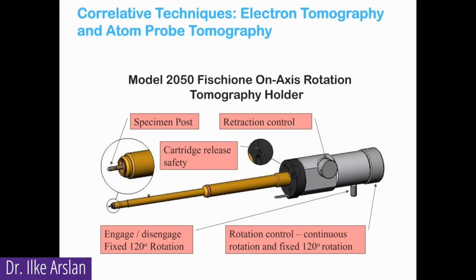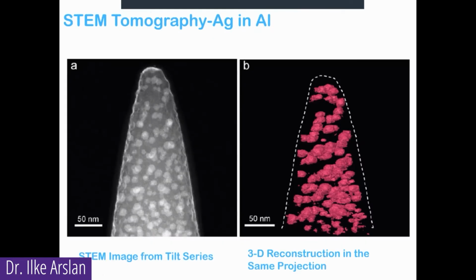And we used this holder that has this removable tip that can fit into a FIB so that you can make your sample and put it on there. And then it fits into this holder so you can do your electron tomography. And then this little stub comes out and also fits into the atom probe so you can do your atom probe microscopy. And so here is what the tip looked like.